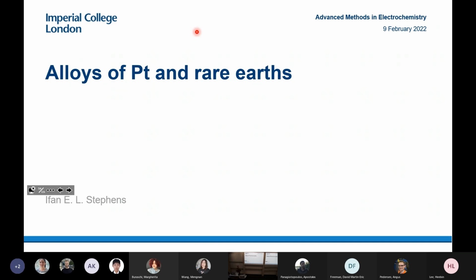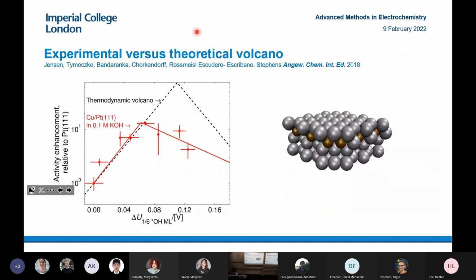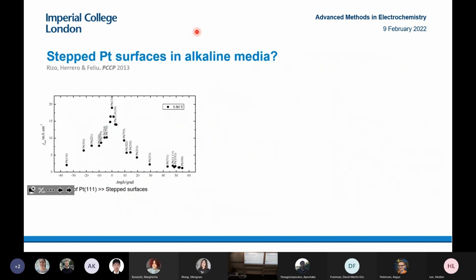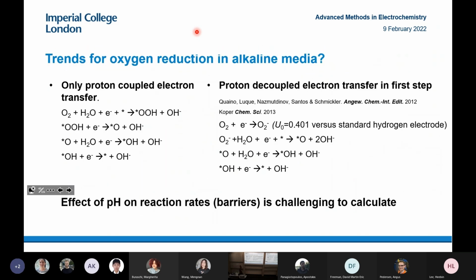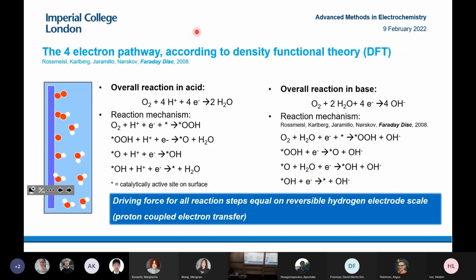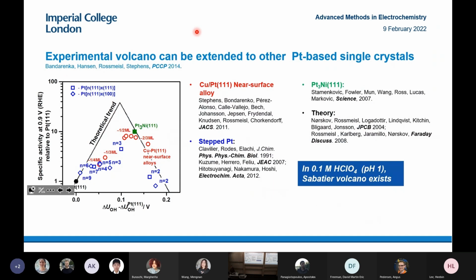Like the monolayer of copper, how are you arriving at that? Yeah, so that's a good question. I didn't go into much detail about it. The way we figure out how much copper we're putting on the surface is we're using underpotential deposition, so that means you adsorb copper at a potential where you can't make bulk copper. We put the copper on, then we stripped it off, so we can calibrate how much we put on that way, using the charge. We checked using XPS to see if the amount of copper was about what we thought it should be, and it usually was. And also the 1/6 monolayer, yes, that's from integrating the charge as well.